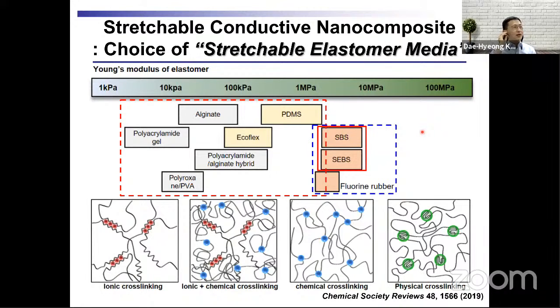And in the case of elastic media, we can use either chemically cross-linked polymers such as PDMS or Ecoflex, or thermoplastic polymers such as SBS or SEBS. In the case of PDMS, for example, the chemical stability is very good. However, to cross-link PDMS, we have to mix the prepolymer with a platinum-based catalyst for polymerization. But unfortunately, if we add a large number of conductive fillers, such as silver nanowires, then the platinum catalysts become inactive. So the polymerization cannot proceed.